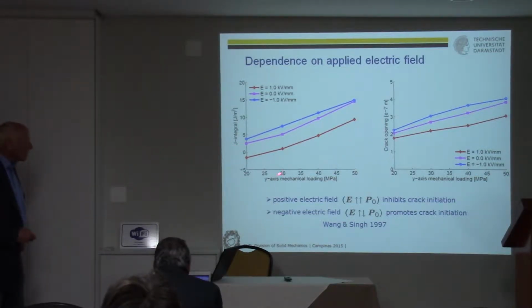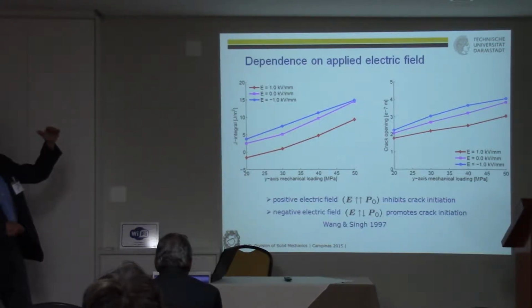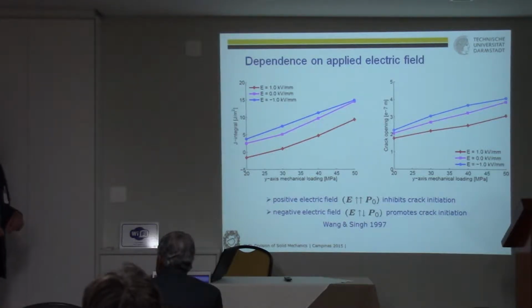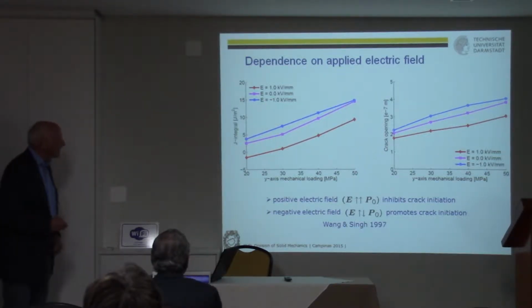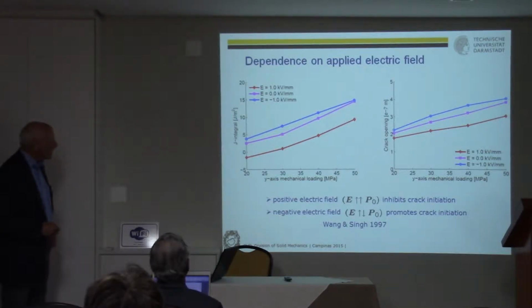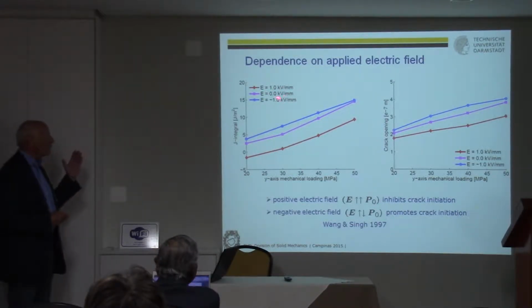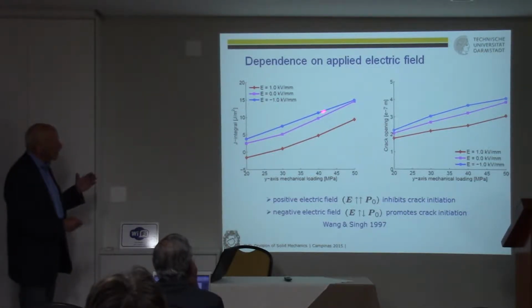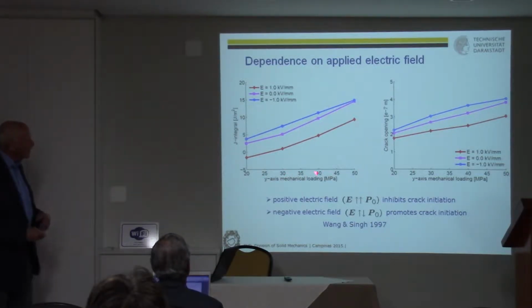And here is the loading, the mechanical loading. And here are three different electrical loadings. Plus means in the direction of the initial polarization, minus means in the opposite direction of the initial polarization, and zero, of course, nothing. This is only mechanical loading. What you see here, if you have an electrical loading in the direction of the initial polarization, this curve lies below the others. And for the negative electric loading, this is the highest, independent of the mechanical loading.